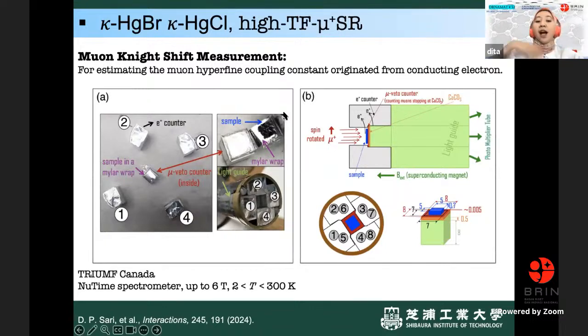Right, so this is the muon Knight shift measurement. I need a very high external field to be introduced in order to sense the magnetism, if we have magnetism in the conducting electron. So this is the schematic of high transverse field μSR. Actually, it's the same, we have counters, but the muon spin is rotated 90 degrees, so we can have a transverse external field up to 6 Tesla. And then we can cool down from 300 to 2 Kelvin.